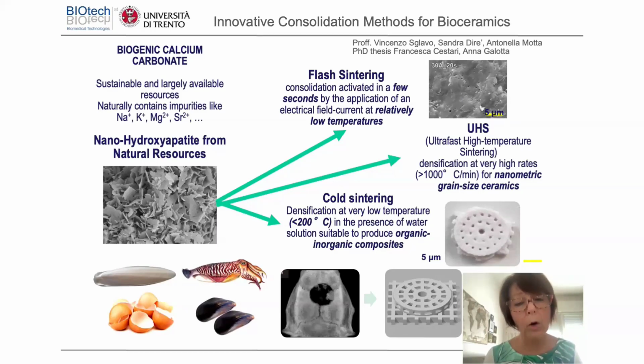Nowadays, we are almost close to room temperature. And this is quite important for a couple of reasons. Not just because the energy involved is lower, so more sustainability, but also because in the mussel shells, for example, there is not just an inorganic phase, there is also an organic phase that is very important for the biocompatibility. And if the process reduces the temperature, even the organic part can be saved, so improving the bioactivity